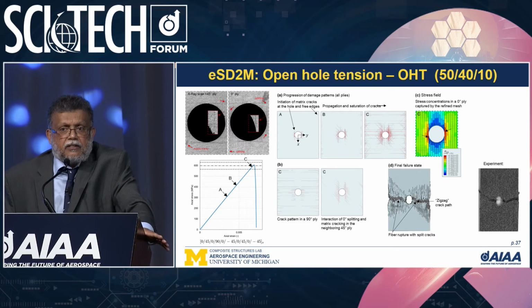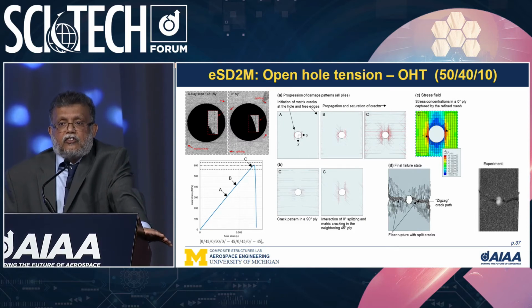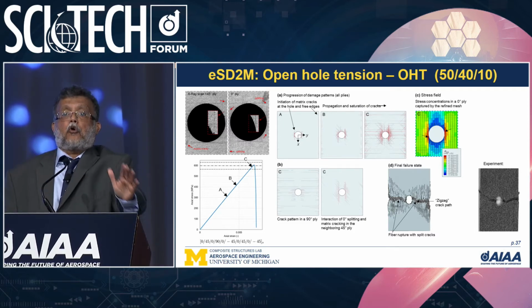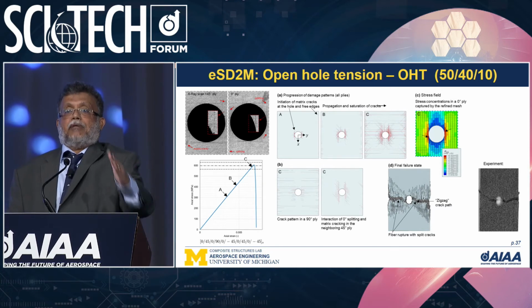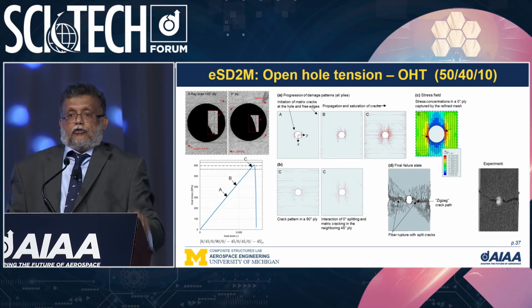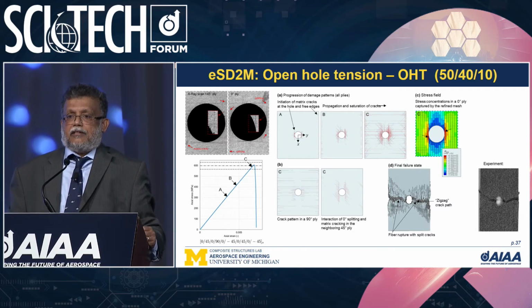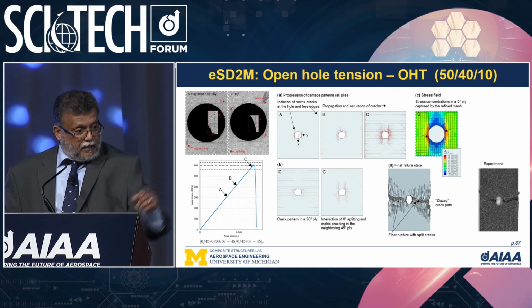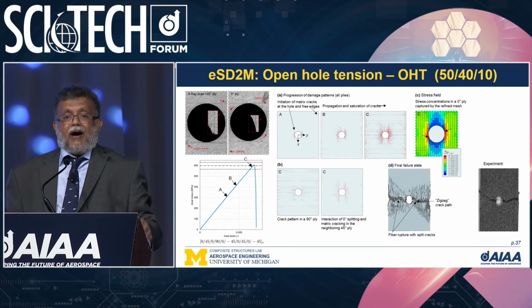But is that of concern? Absolutely not, because the splits do not have enough energy to grow until you keep increasing the energy. So just because you get a split at a notch doesn't mean the laminate is no good. If you look at the final failure load, it's almost twice the load at which the split initially occurs.